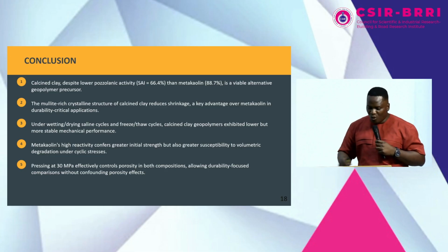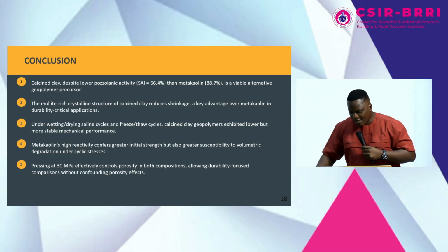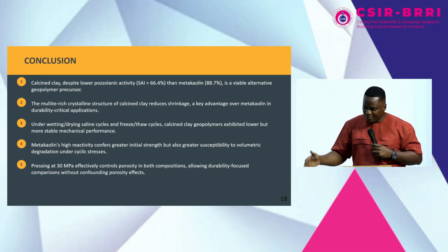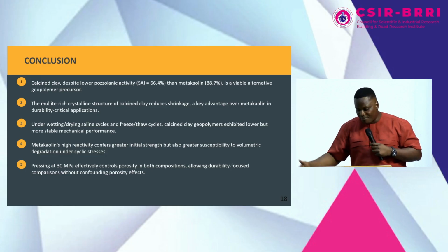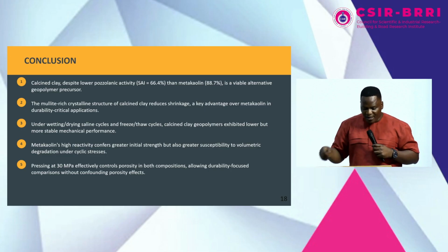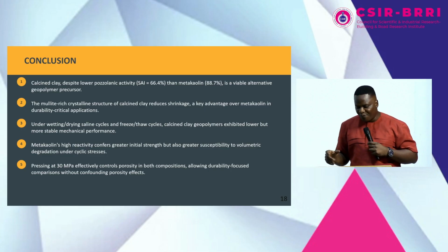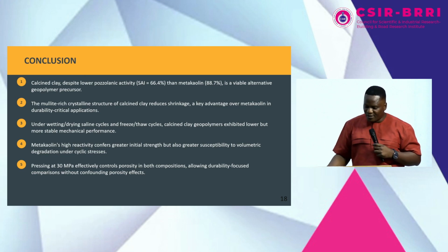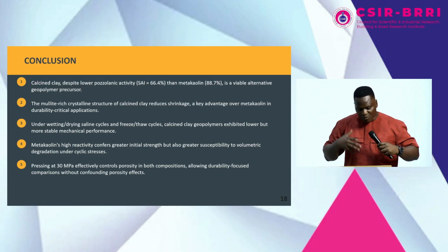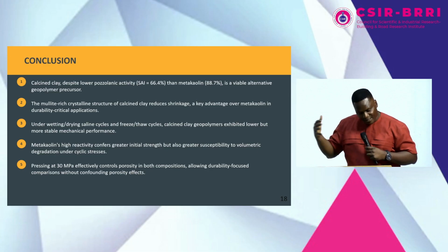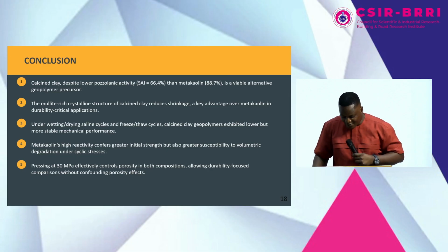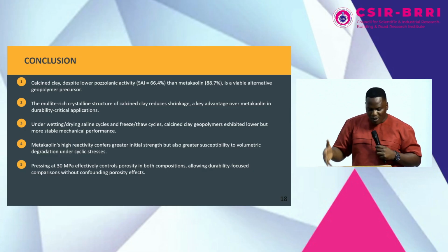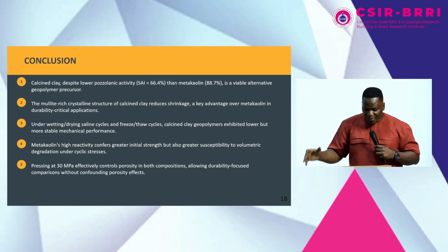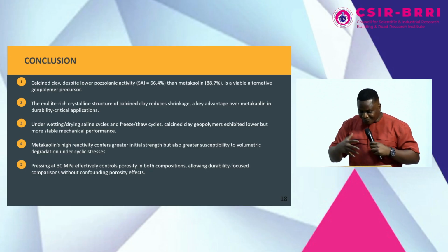Now, calcined clay, despite lower activity index, performs better than the metakaolin. No, calcined clay performs lower than the metakaolin in terms of the strength. However, the mullite-rich crystalline structure of the calcined clay reduces shrinkage, a key advantage over metakaolin in durability-critical applications. Then again, under the wetting and drying saline cycle in the sodium chloride environment and the freeze and thaw cycles, the calcined clay geopolymers exhibited lower but more stable mechanical performance. And I've explained that that's because of the presence of the mullite phase.